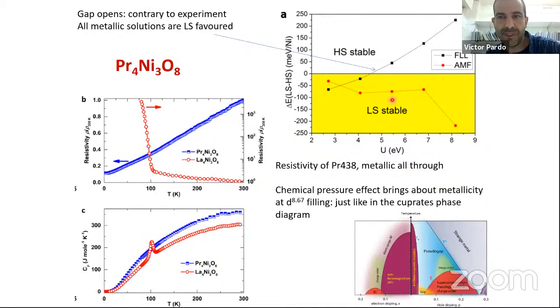We have tracked pretty well that this particular flavor of the LDA plus U agrees with experiments in these nickelates. And in this case, our prediction was that this system would be low spin and it would be metallic. And indeed it is. You see the resistivity of the praseodymium 438 is this blue curve here, and it's a metal. And also there is no trace of a charge density wave in